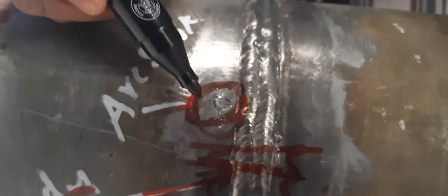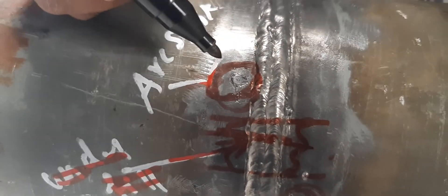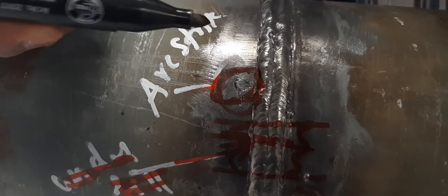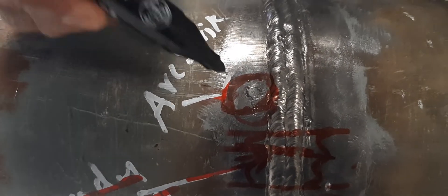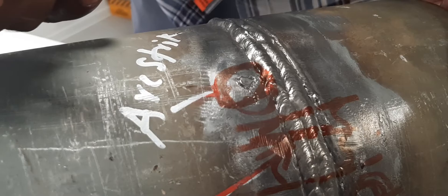This is arc strike. This is a lack of welder ability - during welding they directly touch the base metal, so arc strike happens. We can remove it and then do buildup for the welding, because later we can get crack also if not removed properly.